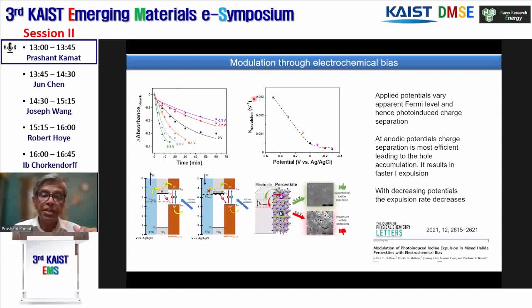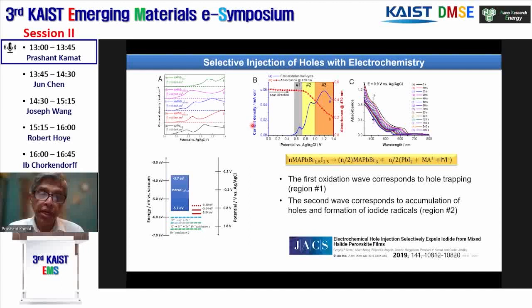And so again, we can measure the expulsion rate versus the potential. And you can see here the dependence has become more negative. Now you are putting more electrons back into this material, and you're changing this Fermi level, making the hole accumulation less probable. As a result, you see a very decreased rate. So again, it points to the fact that the hole accumulation on the iodide is responsible for the movement of the halide.